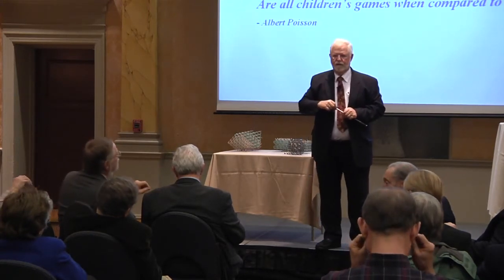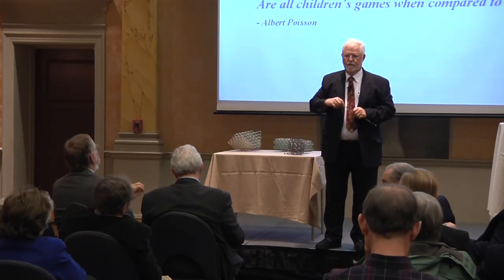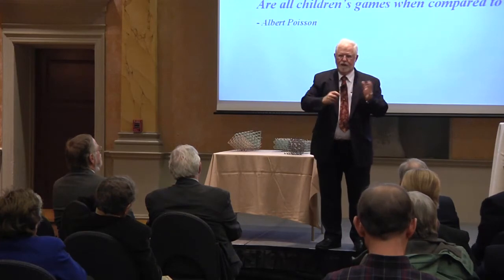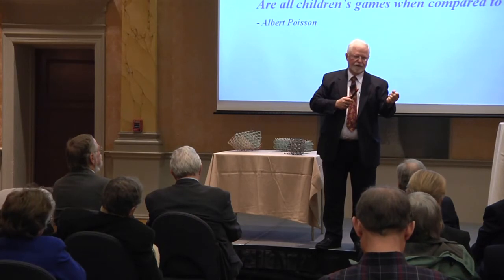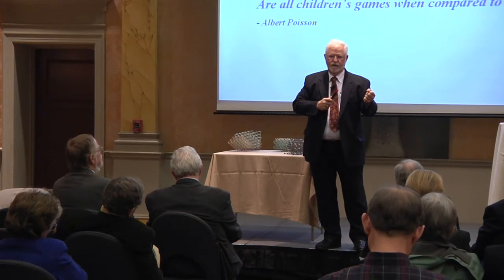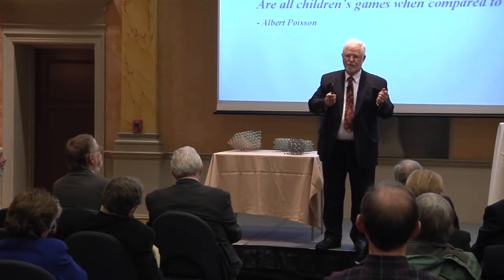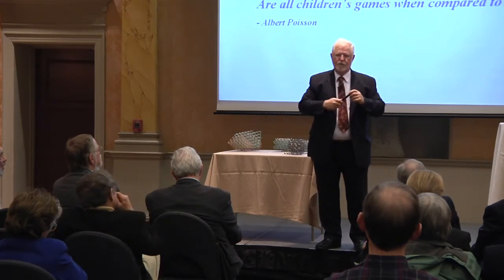And I think the diamond is too atomically dense to be host to interstitials? That's a very good question. One of the problems, I want to expand on the answer: it is so atomically dense, we can get very few atoms into it. Boron will fit in, nitrogen will fit in, silicon will fit in with a vacancy, nickel will fit in with a vacancy, hydrogen can fit in and actually move in the lattice, carbon interstitials can be made and they move around. Vacancies are not mobile until you get to about 800 or 900 degrees C. When I say this lattice is cold, not much moves in it.